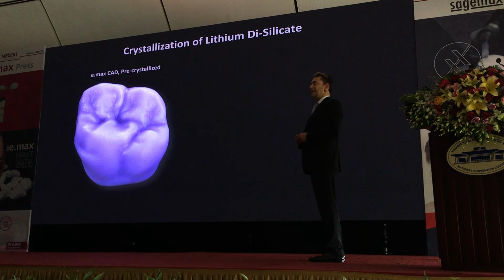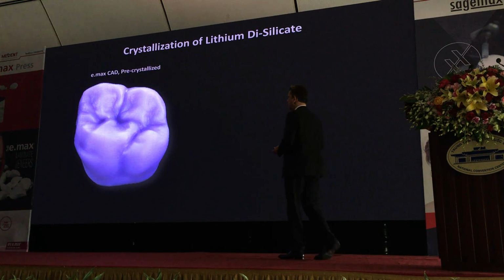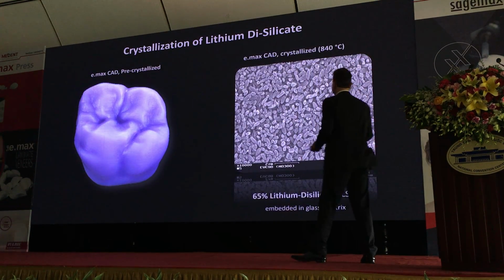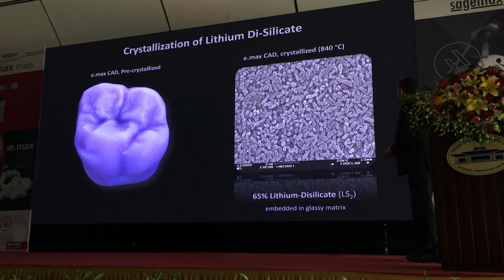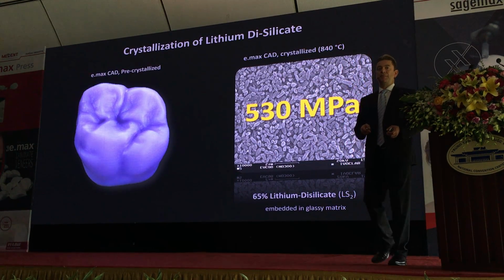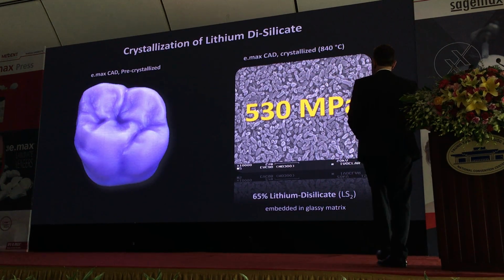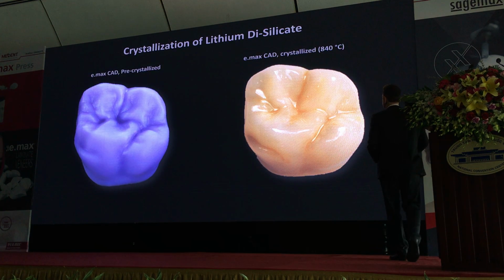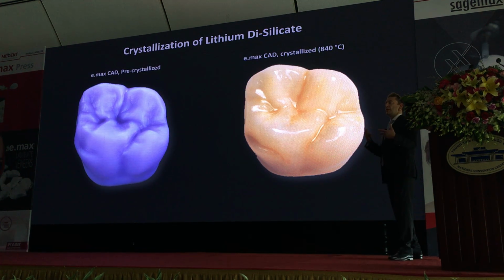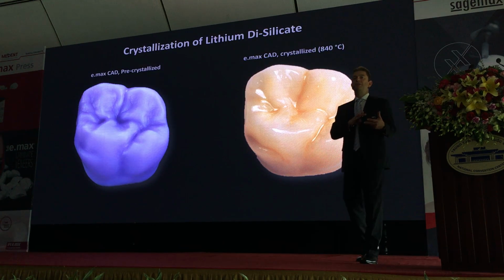And then we have to crystallize it. So we place this blue crown into a furnace for crystallization. Now these crystals are growing and becoming more dense. Okay, like this. So after crystallization, you can see the crystals look very different. They're much larger. Now we are increasing the strength to 530 megapascals. So before, in the blue stage, it was only 130, and after crystallization, we are at 530, and the crown becomes tooth-colored. And also we can glaze and stain at the same time.